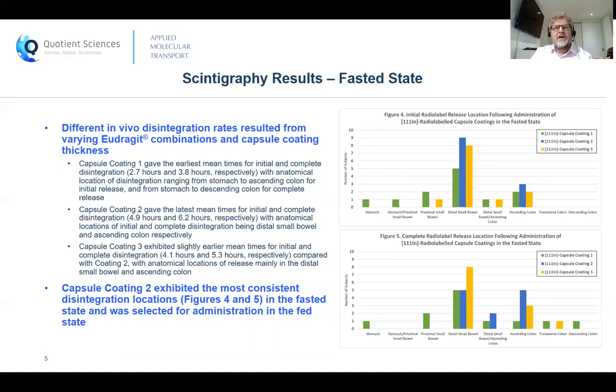Capsule coating 1 gave the earliest mean initial and complete release times at 2.7 hours and 3.8 hours respectively, and the green bars in the chart show the early and relatively wide spread of GI release locations for this formulation. Capsule coating 2 gave the slowest mean times for initial and complete release at 4.9 hours and 6.2 hours respectively, and in blue on the charts, all the release was located between the distal small bowel and the ascending colon. Capsule coating 3 gave mean times between those of the other two formulations, and the yellow bars show a larger range of release locations in comparison to coating 2.